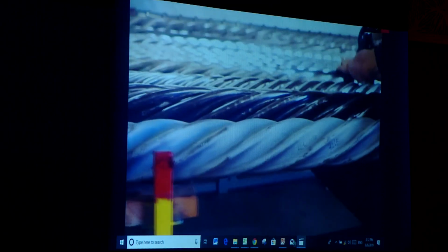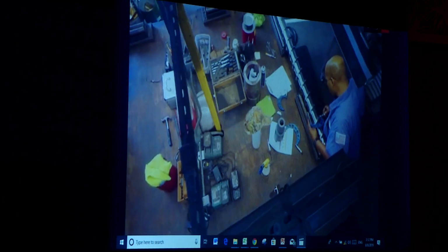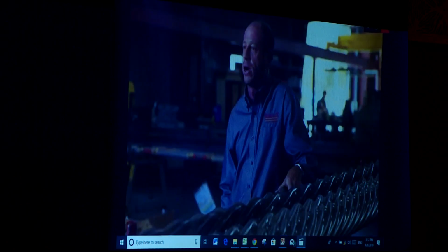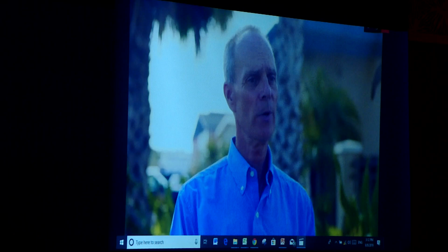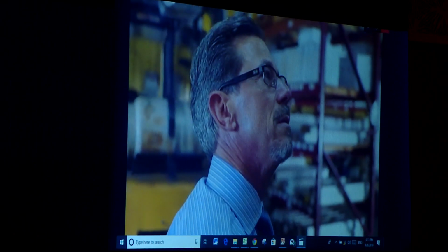When we have a customer that has a problem or an industry that's suffering from a problem, we go directly to the folks that are running the machinery and we ask them what exactly are the problems that you're having. If you ask anybody globally about surface treatments of feed screws, they would say, oh yeah, we use these people in Florida, Extreme Coatings. Extreme Coatings specializes in applying high-velocity oxygen fuel coatings, otherwise known as HVOF, to surfaces to resist extreme applications of wear. Automotive parts with glass fiber, metal injection molding, PVC corrosion resistance, all the ways that processing resins in an injection machine or an extruder can lead to rapid wear or corrosion of the components. They make more money by not losing money by premature wear conditions.